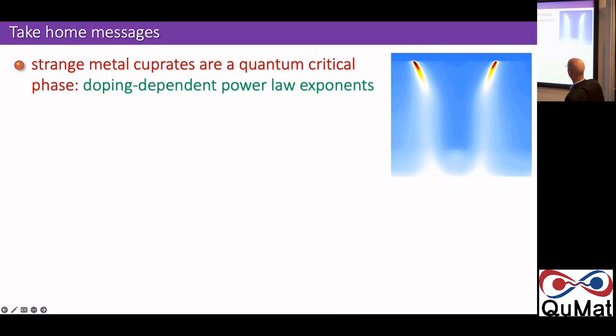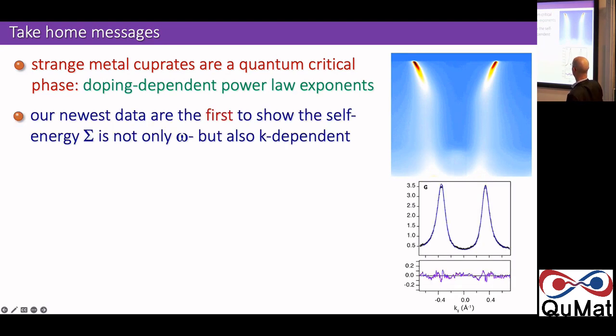Okay, so take-home messages. Strange metal cuprates are a quantum critical phase. They show doping-dependent power law exponents, which we could see in the transport as a function of temperature, but in photoemission, we can also see the frequency dependence of these systems. Our newest data are the first ARPES data to show in a really controlled way that the self-energy is not only a function of omega, but also of K. So for the theoreticians, that will sound obvious. But the experimental ARPES community has been, for 20 years, obsessing about the fact that it's only the frequency dependence that matters, because otherwise I can't use my Lorentzian and I don't know what to use.